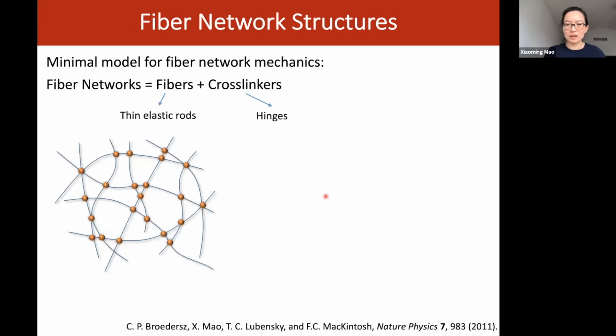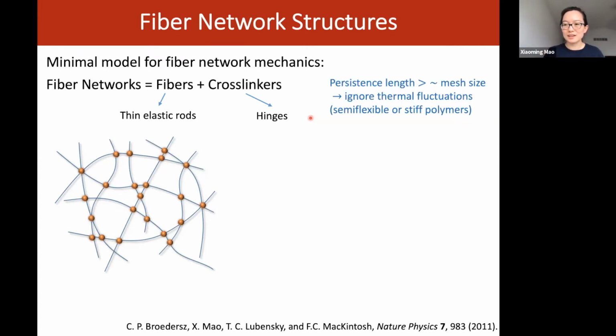So how do we understand this mechanical critical point? To do that, let's start by thinking about a very simple minimal model of fiber networks. So we throw away the complicated macroscopic details and just think about fibers as thin elastic rods and the cross-linking points as hinges that connect these rods together. I'd like to mention that by doing this, we're assuming that the thermal fluctuations can be ignored. So we are in the regime of persistence length greater than the mesh size of the network, and you can model these in an athermal way. So this applies to, for example, semi-flexible and stiff polymer networks and the fiber networks of macroscopic fibers, and not to flexible polymer networks.